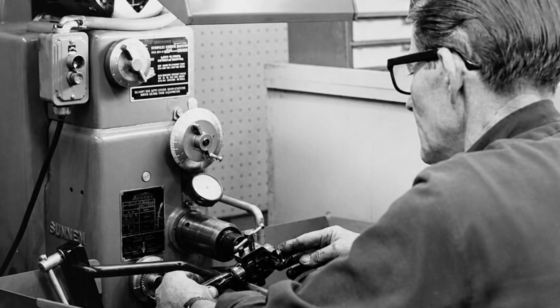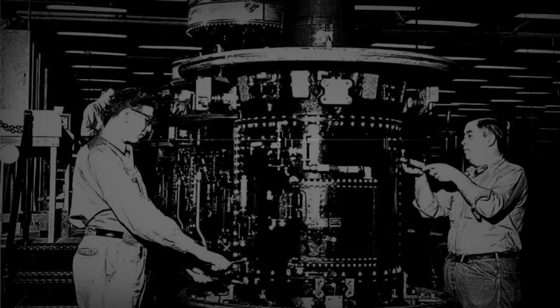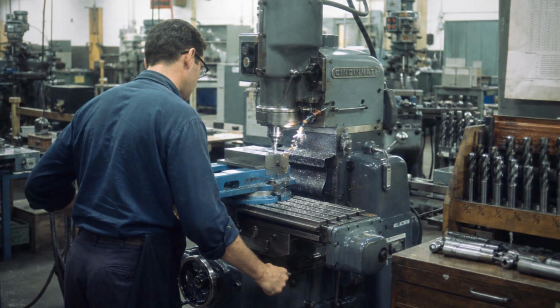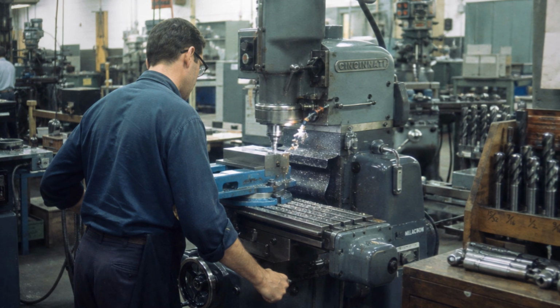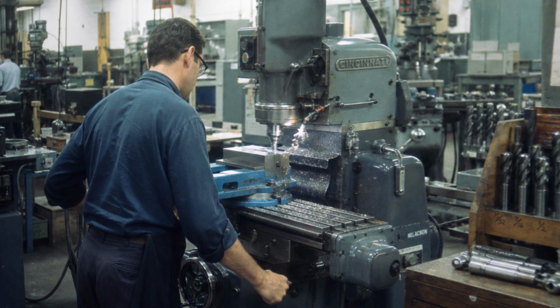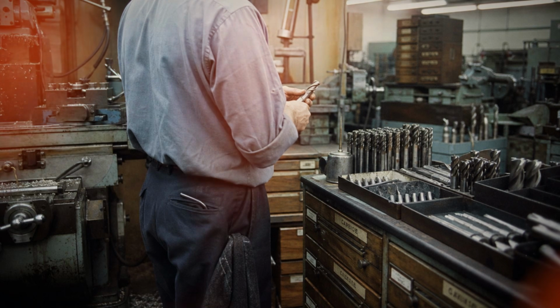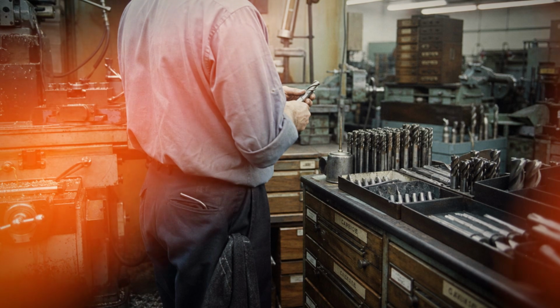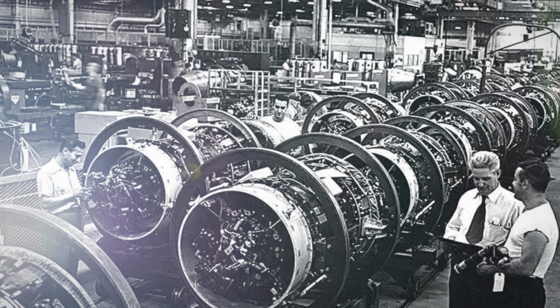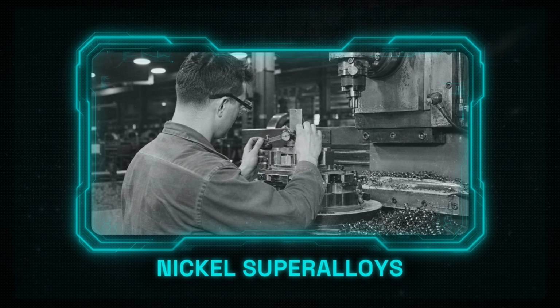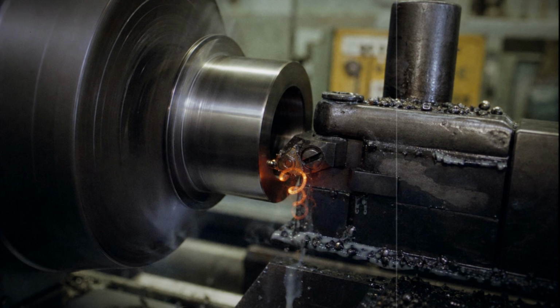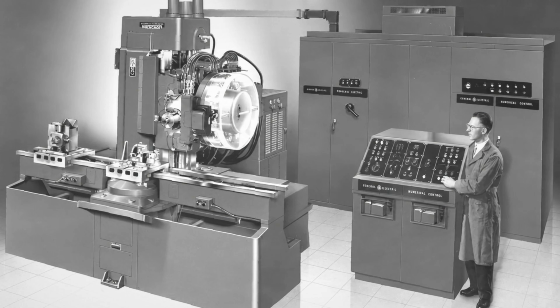The pricing arrangement did not survive the peace. The 1948 ruling went against GE, and in the decades that followed, carbide became cheap enough to grind into solid drills and end mills, whole tools of the material that had once been priced above gold. And the war's aftermath handed machinists a new opponent: jet engines, built from nickel superalloys that work-harden under a dull edge and hold their strength at temperatures that destroy tool materials. That bill comes due later in this story.